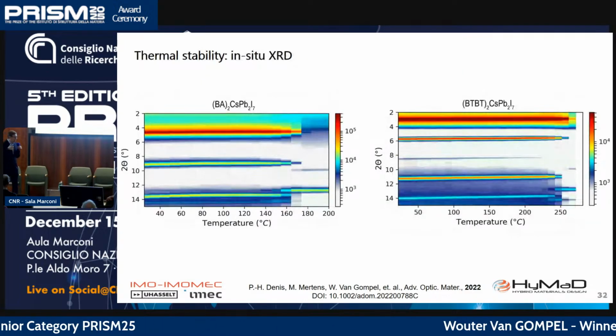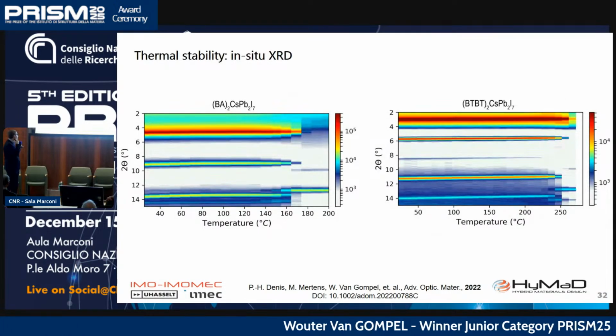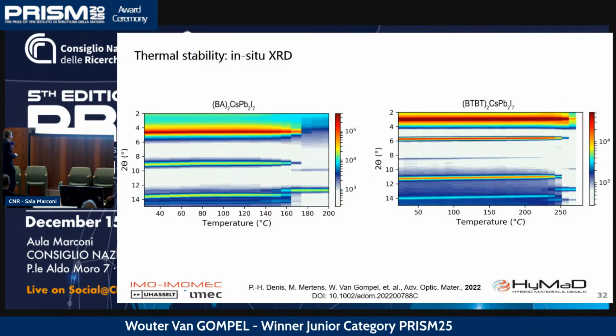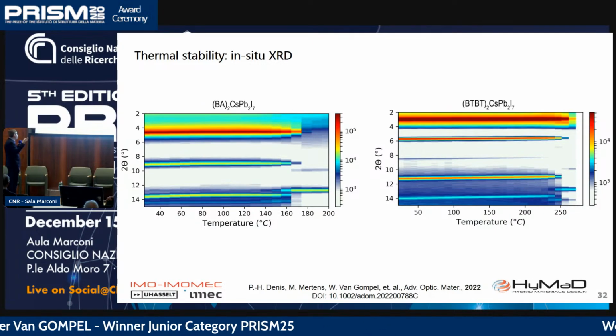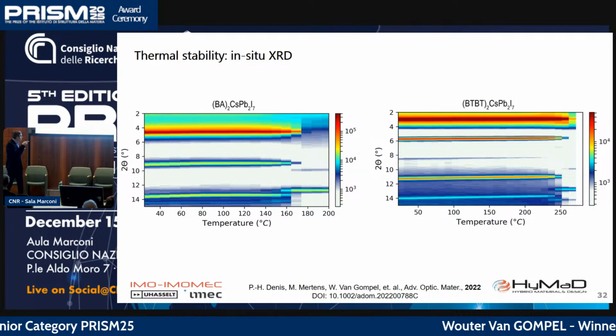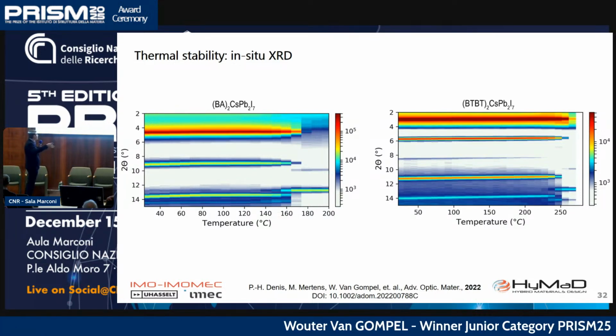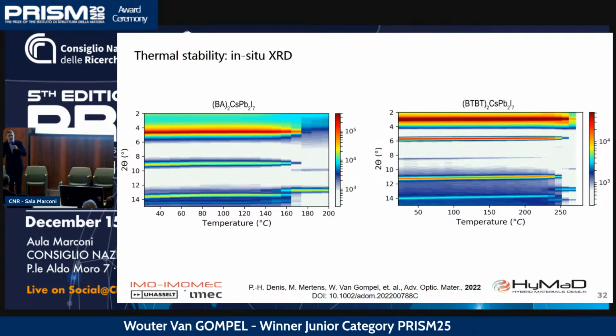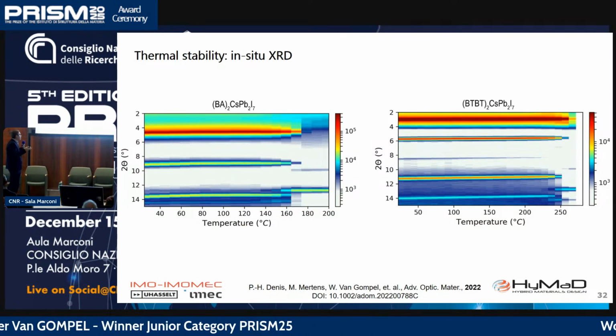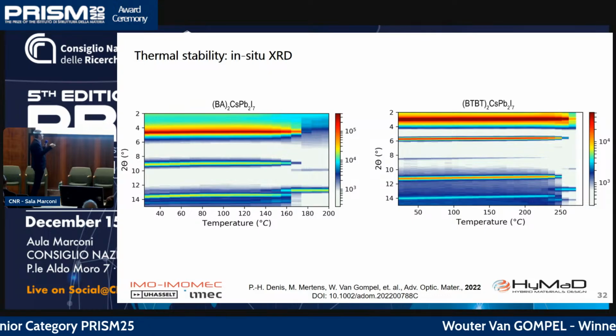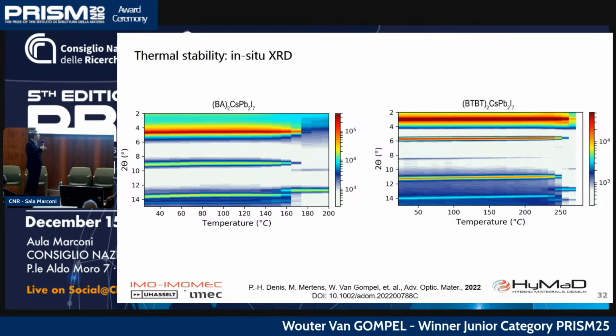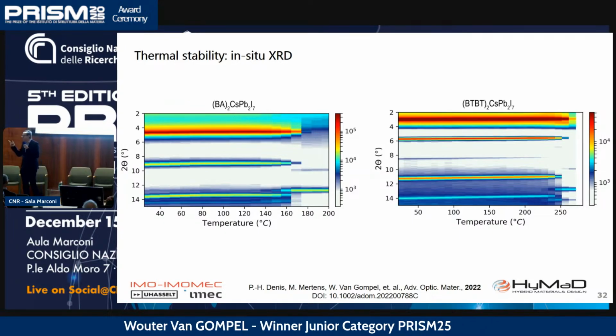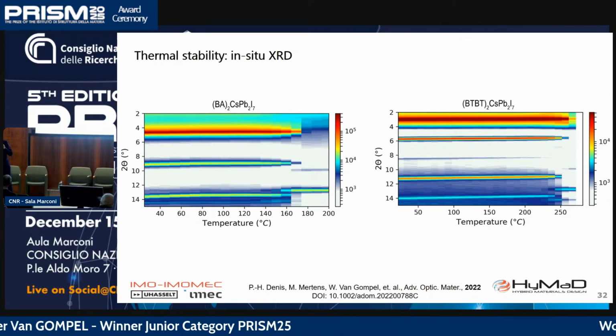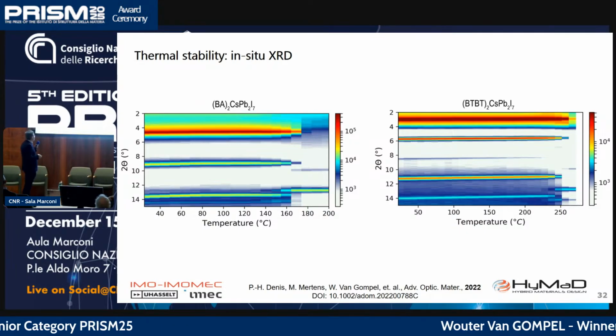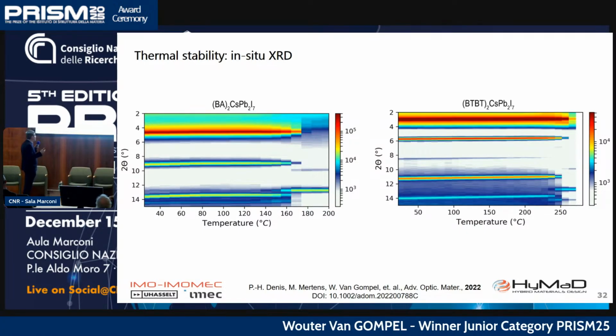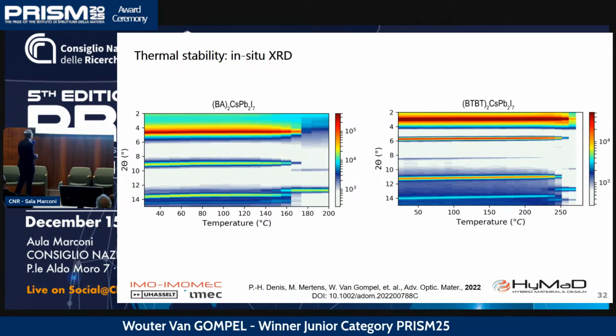It's not only moisture stability, also temperature. So if you look at these in situ X-ray diffraction as a function of temperature, you see that the reference material starts to degrade at 150, let's say, 150, 160. And the one with the rigid molecules is almost 100 degrees higher temperature. Okay, you may say your electronic application will not reach 200 degrees, but it's a kind of accelerated aging. If it survives until a temperature of more than 200, it will also survive for a longer time at 85. And as you may know, a solar panel exposed to high sunlight reaches 85 degrees. So also in temperature stability, you can usually improve the stability by tuning the right organic molecule.